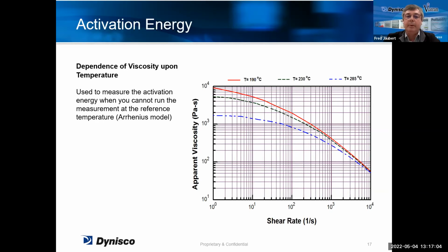If you are running a system online and you want to measure polypropylene, the standard test, for example, for melt index or viscosity for polypropylene is 230 degrees C. But on the extrusion line, maybe you are going to run at 260 or 270 degrees C. Using the activation energy, it will allow us to recalculate the value expected at 230, even if you are measuring it at 280 degrees C or 270.